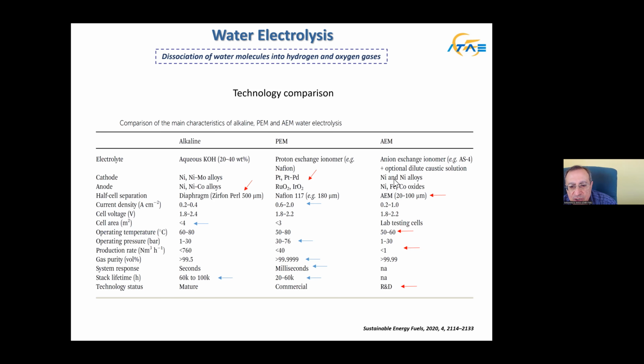We use non-critical raw materials like in the alkaline. We can increase the current density, not at the same level of PEM, because the mobility of hydroxide is not the same as the mobility of protons, but we can really approach practical current density. So we can minimize materials. We can combine advantages of alkaline and PEM, also in terms of gas purity and high pressure.